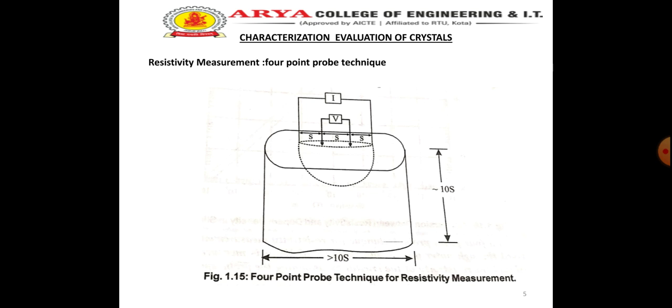Routine evaluation of crystals, also called ingots or boules, involves testing their resistivity, evaluating their crystal perfection, and examining their mechanical properties like size and mass. Other less routine evaluation includes measuring the crystal's oxygen, carbon, and heavy metal content. The evaluation of heavy metal content is made by minority carrier concentration measurement and neutron activation analysis.